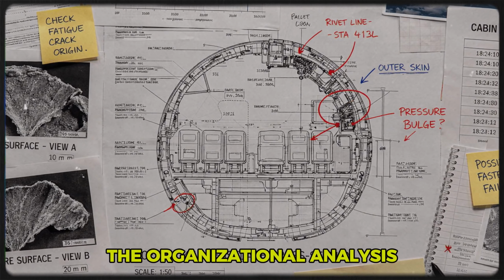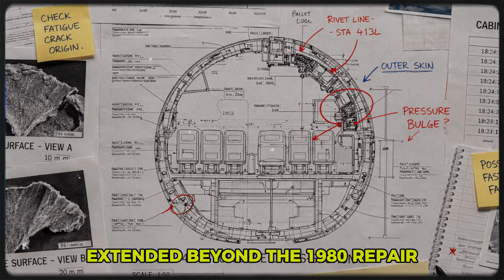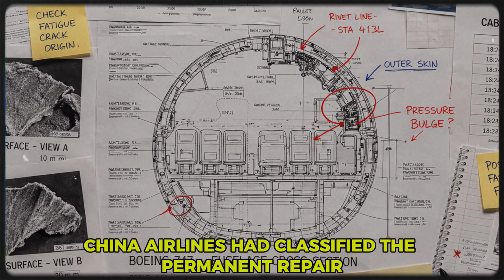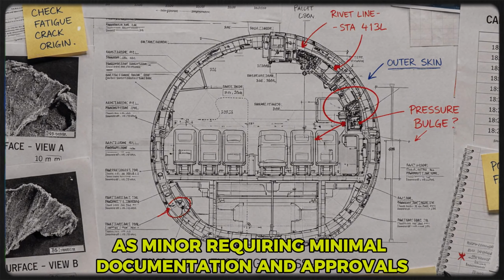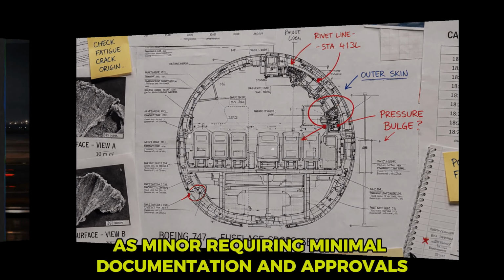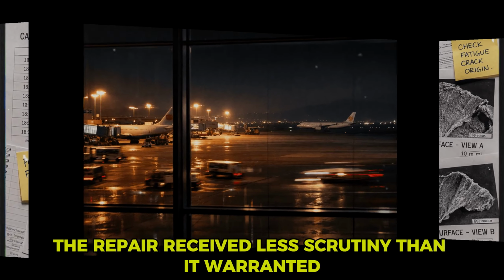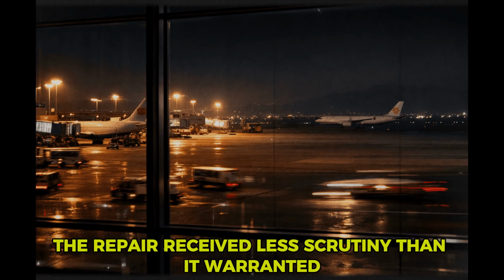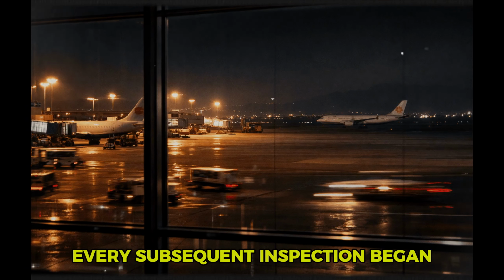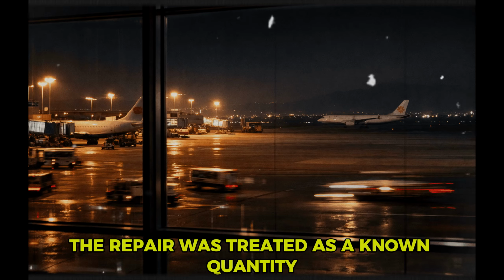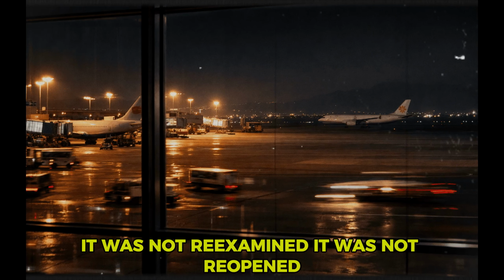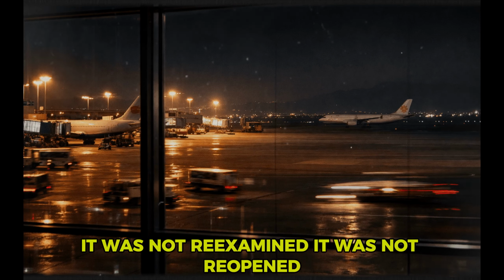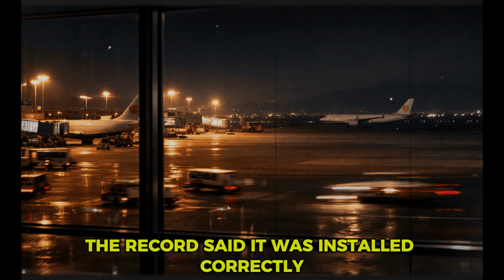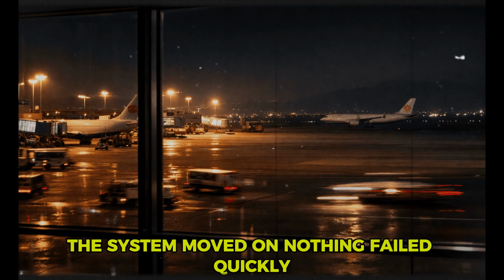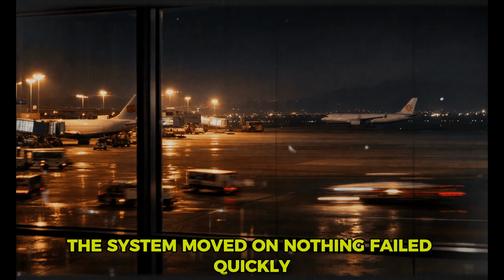The organizational analysis extended beyond the 1980 repair. China Airlines had classified the permanent repair as minor, requiring minimal documentation and approvals. This meant the repair received less scrutiny than it warranted. And once the records indicated compliance, every subsequent inspection began from that assumption. The repair was treated as a known quantity. It was not re-examined. It was not reopened. The doubler was there. The record said it was installed correctly. The system moved on. Nothing failed quickly.